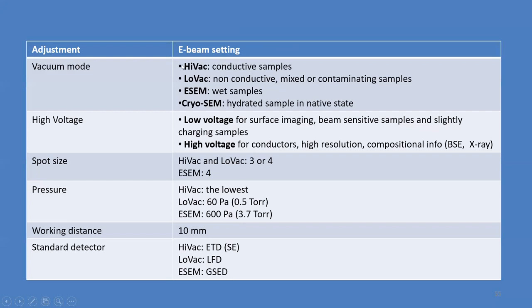And then there are these vacuum modes. High vacuum mode is good for conductive samples. But most biological samples are non-conductive, so you have to use low vac for mixed samples. So there are different modes. For wet or hydrated samples, you have cryo-SEM. Low voltage is typically used for surface imaging and beam sensitive samples, and high voltage for conductive samples.